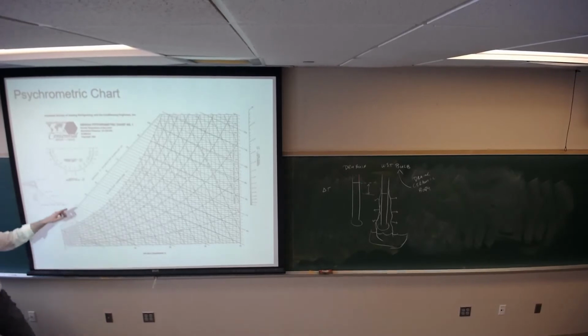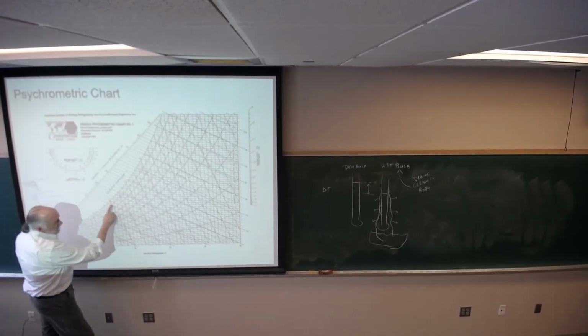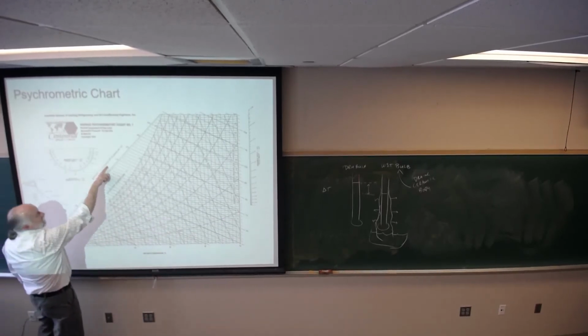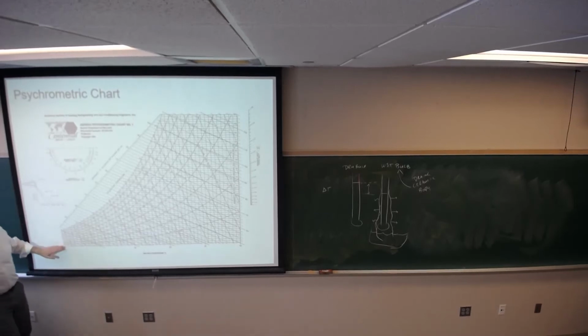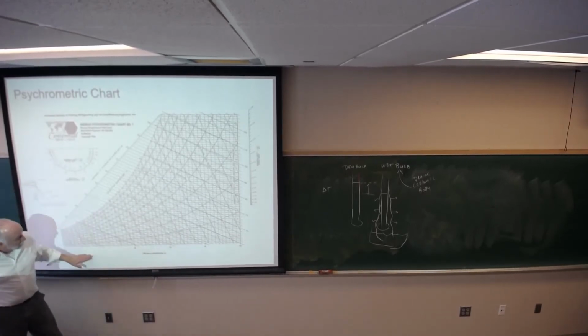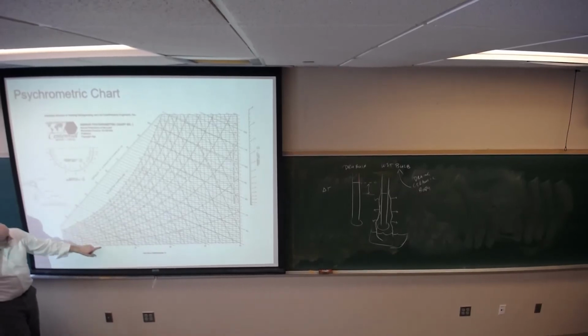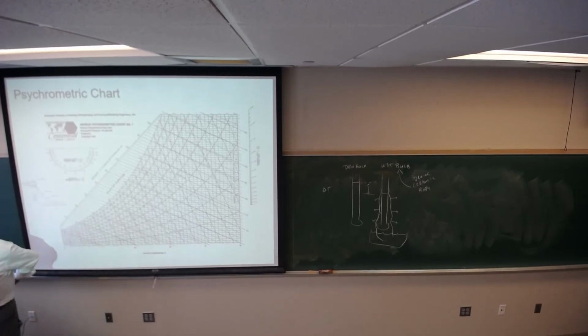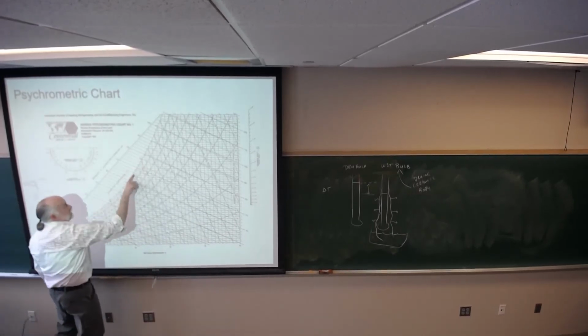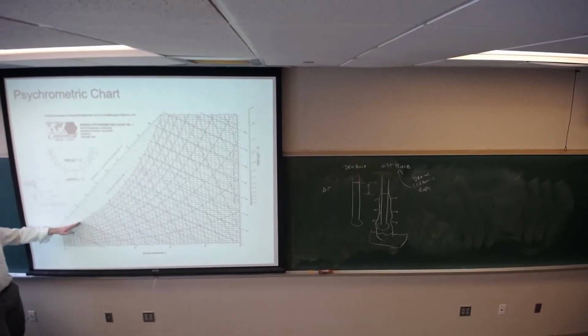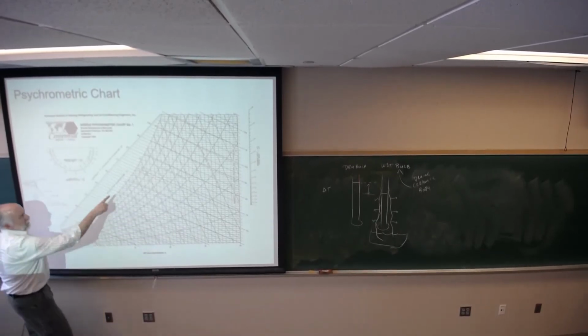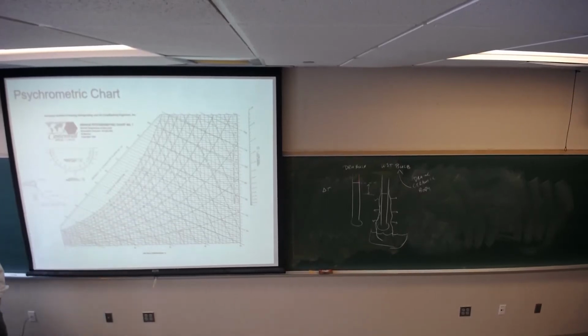And they do that here with enthalpy, which are these lines that move across in this fashion, and they are kilojoules per kilogram of dry air. First piece is right here. This is the x-axis, the dry bulb temperature. So you have 0, 10, 20, 30, 40, 50 degrees C. And then this curve here is the wet bulb temperature, or the saturation temperature. So this curve is actually the 100% saturation level. So you'll see that 10 relates to 10, or 20 here is 20 there. That means your wet bulb and your dry bulb are the same temperature, and they are the same because there's no room for evaporation. There's no room in the air to handle moisture.